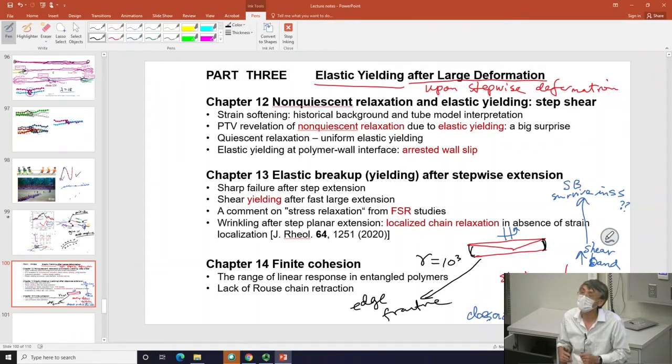So it's really demanding to learn about startup shear and whether shear banding survives in steady state, because you run the risk of the sample suffering from edge instability. The sample just doesn't behave well when you shear for too long.